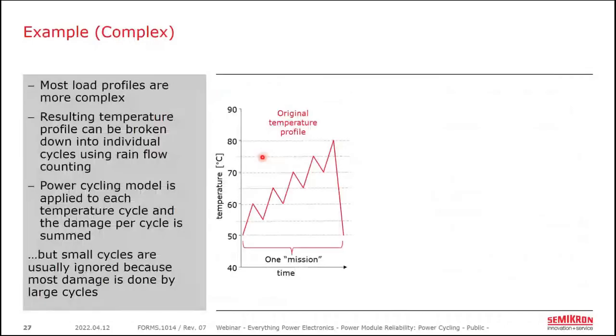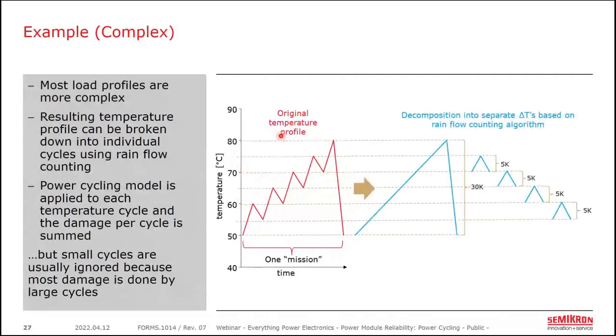Now, in some cases, the calculated temperature profile will be much more complex as that junction temperature varies with load and frequency. And here we might have multiple temperature swings occurring over one total load cycle, which we're going to call a mission or a mission profile. And so what we do in this case is that we need to break down that complex load profile into individual temperature swings. And then for each individual temperature swing, we can derive our own delta Tj, mean junction temperature, and heating time. And the way you do this is with something called the rainflow counting method.